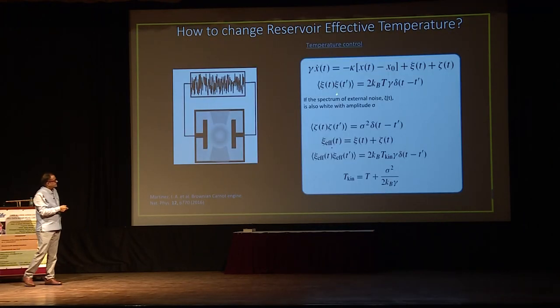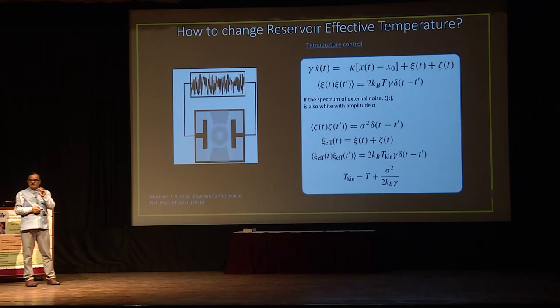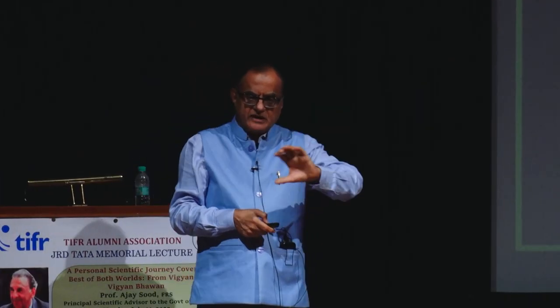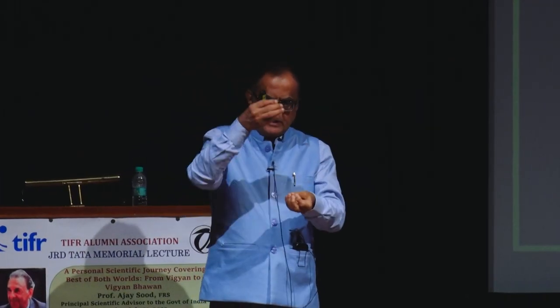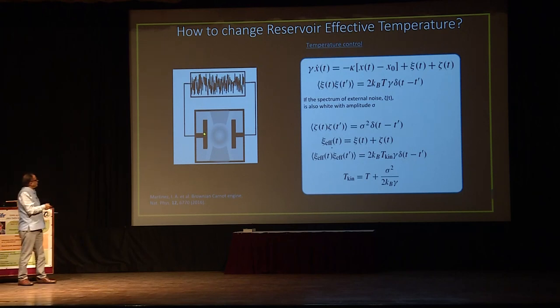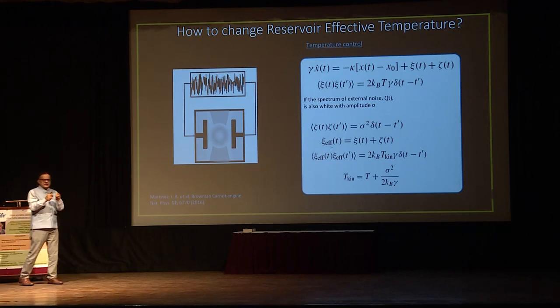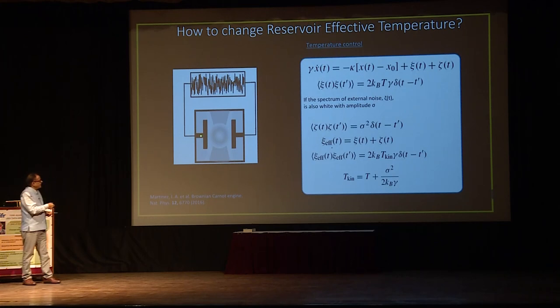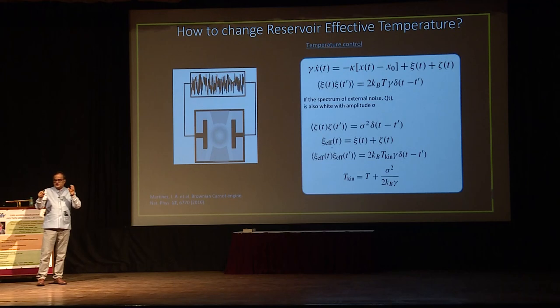What we did is, now we don't vary the temperature of the water by heating and cooling. You put an electrode around the trap where you apply white noise voltage. Voltage is applied, it's an electrophoretic mechanism, and it is applied randomly. It's a white noise. So it's a 2 kilohertz voltage varying from plus 0.5 volt to minus 0.5 volt.